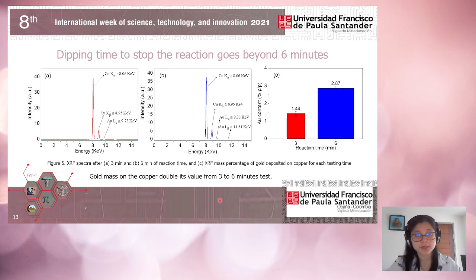Another evidence of the reaction going beyond 6 minutes was the XRF results. On figure 5, we can see the spectra. In the case of figure 5a, we can see the spectra of the 3-minute sample. These peaks correspond to copper and this one to gold. Then you can see for the 6 minutes the same spectra, here for copper and here for gold.